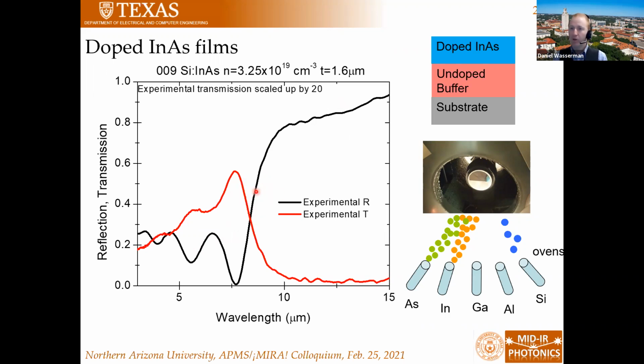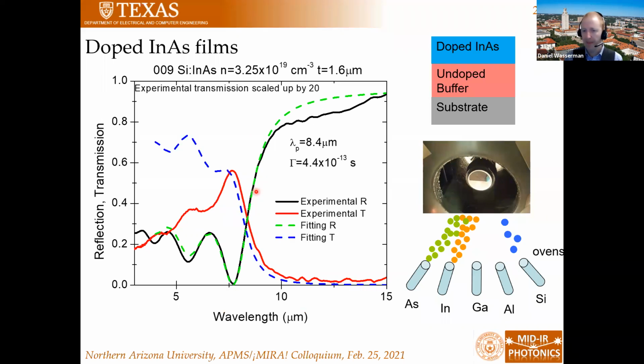So this is one of the very first samples that we ever grew, and you can fit this using the Drude model that we just described in the previous slide. So you can assign a plasma wavelength or a plasma frequency and a scattering rate. That's a damping term. And you can see that you actually get a remarkably good fit when you model your indium arsenide material simply as a Drude metal with some background permittivity, and then just using a transfer matrix method to calculate the reflection and transmission.